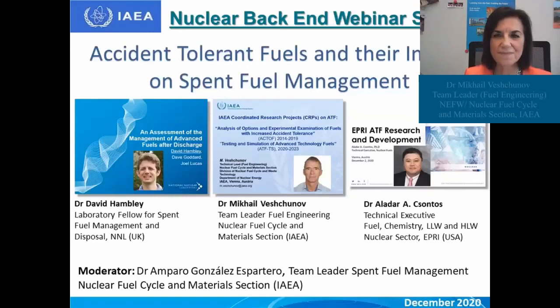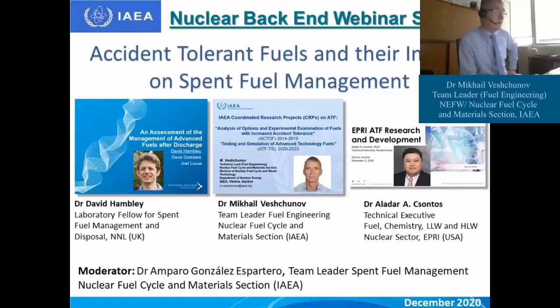Yeah, good question. Because you see, research is going step by step. Up to now, it was more focused on normal operation conditions and local conditions, where these effects are not so important. But going above 1200, somewhere at 1350 centigrade, a eutectic of chromium with zirconium is observed, and this is currently under investigation in many research centers, in Karlsruhe, in France.